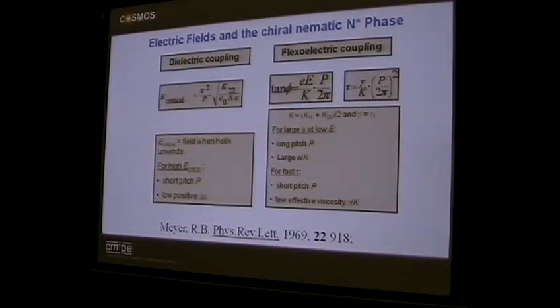And most liquid crystal molecules are either pear-shaped or banana-shaped. I stole bananas this morning. When you have a system of bananas, or pear-shaped molecules, normally, if they're undistorted, the dipoles up and the dipoles down cancel out. But as you distort the system, the dipoles start to align. You generate polarization. That's the flexoelectro-optic effect.